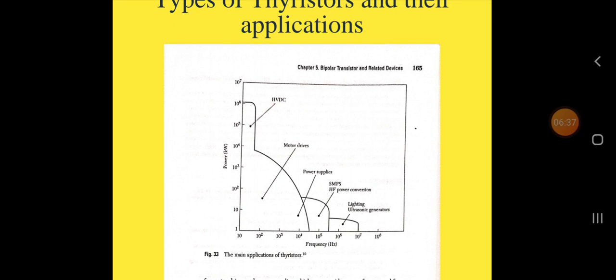For certain switching devices such as high voltage thyristors, as we have discussed earlier, large chip areas are used. Frequently an entire wafer is used for a single device. This size imposes stringent requirements on the uniformity of the starting material. To obtain homogeneous distribution of dopants, we use a float zone silicon slice that has an average doping concentration well below the required amount. The slice is then irradiated with thermal neutrons. This process is called neutron irradiation.